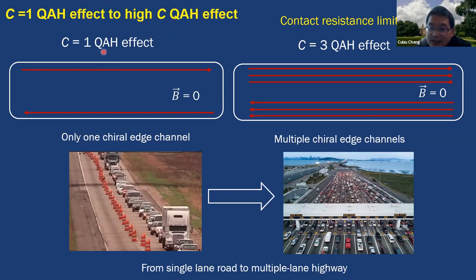This is the C equals one quantum anomalous Hall effect. There is only one chiral edge channel. So when the electron travels from the chiral edge channel to the normal metal contact, just like a car from the highway to the downtown through a single lane, it usually takes a very long time.